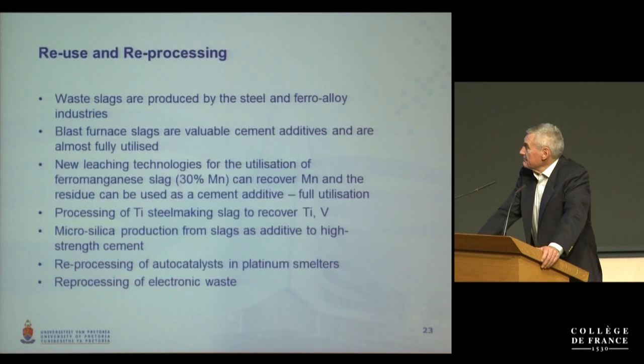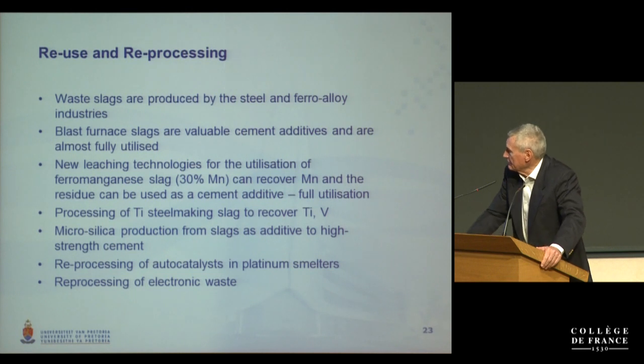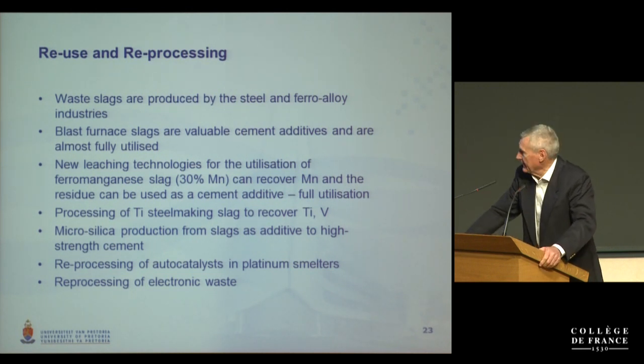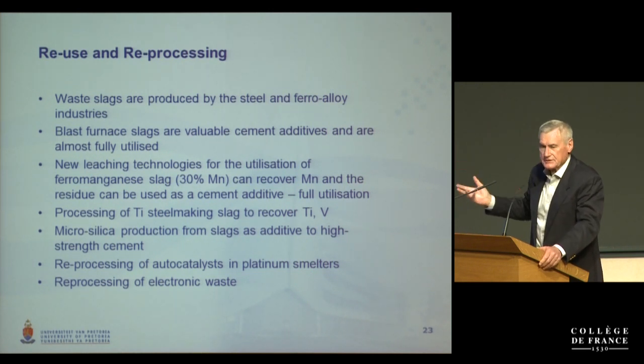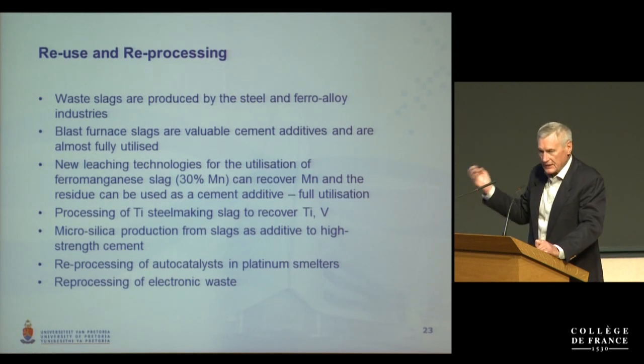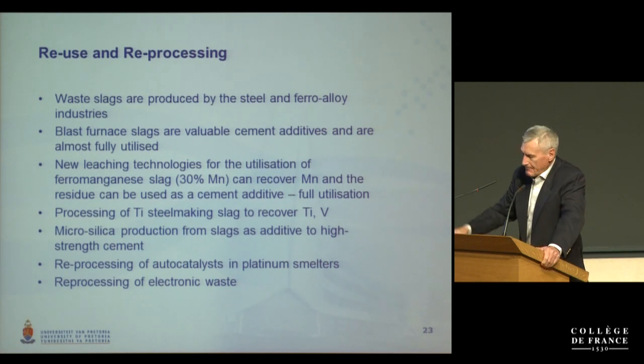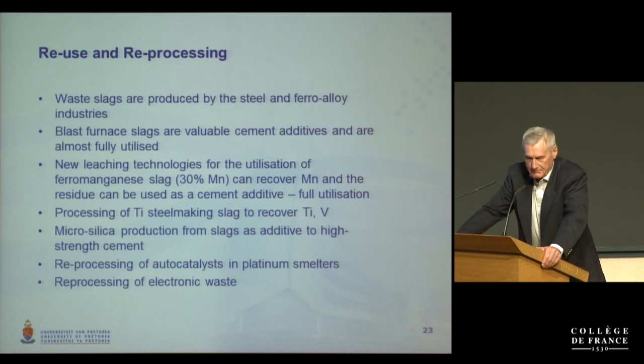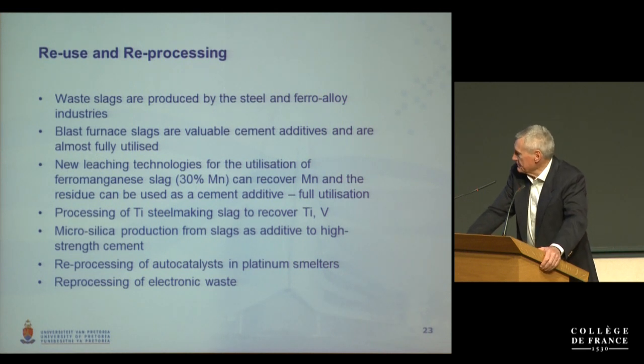Then with regard to reuse and reprocessing, waste slags are produced by the steel and ferroalloy industries. For instance, blast furnace slags are valuable cement additives, and they're almost fully utilized. We are looking at new technologies for the utilization of ferromanganese slag, which still contains a lot of manganese, to recover the manganese and use the residue as a cement additive, because the residue contains gypsum and microsilica, which is quite valuable for cement. There's another effort in processing of titanium steelmaking slag from our vanadium industry to recover residual titanium. That slag contains about 30% titanium and about 0.5% of vanadium. So we have a research program in that area.